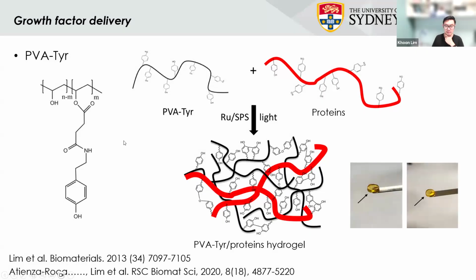So one thing that I'll talk about is some of the work we did in growth factor delivery. For example, we have been designing this polyvinyl alcohol-based delivery vehicle. So we put a tyramine on there. This ruthenium sodium persulfate system that I touched on at the start has this really advantageous mechanism where if a protein has a tyrosine group on it, or a phenyl moiety, this tyrosine group can form a biphenyl bond, or a covalent bond, with the tyramine on my PVA chain. So if I mix them, add my photoinitiators, and shine light, I form these really beautiful cross-links between them. And because my polymer is degradable due to this ester bond here, as these ester bonds are cleaved over time, I can slowly release these proteins of interest out from the system.